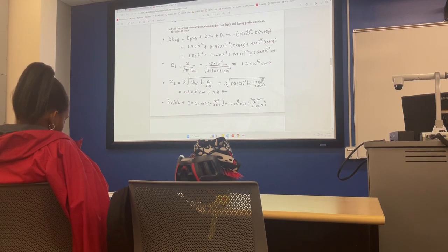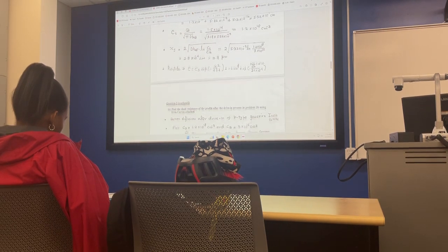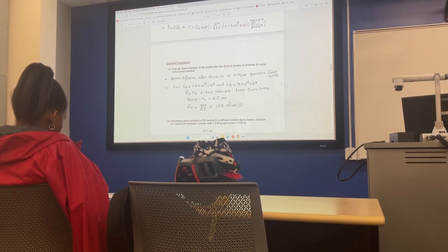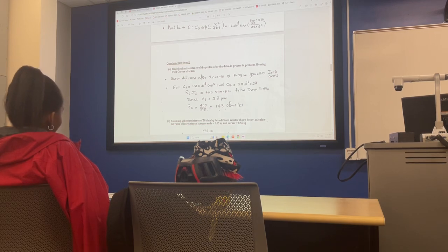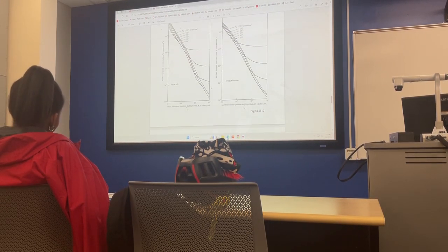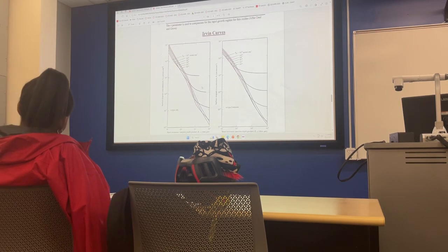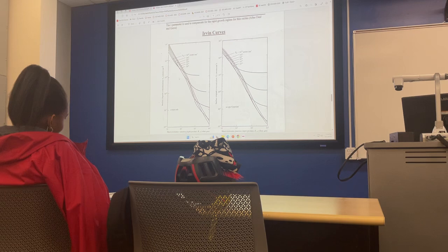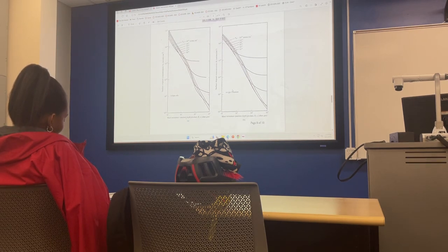So once you got this, I said, okay, tell me what is the sheet resistance. You got all these, so there must be a sheet resistance, and that's the next problem. But I said to get the sheet resistance, use the Irvin curve, right? So I know the surface concentration and I know the substrate concentration, right? That's all I need to read the Rs Xj. So you go into your, but it should be Gaussian because it has been driven. Error function is only that. So some of you started using this, but you go to, I did not draw the line.